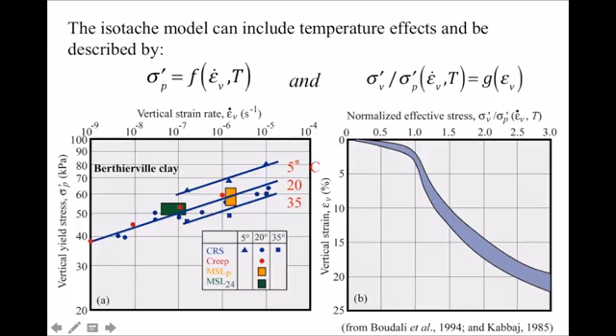So, in fact, the pre-consolidation pressure or vertical yield stress, which was a function of strain rate, is also a function of temperature. And this is shown here for the Berthierville clay, where you have the line in the middle at 20 degrees, the upper one at 5 degrees, and the lower one at 35 degrees. But when the vertical effective stress is normalized with respect to the pre-consolidation pressure associated with the temperature and the strain rate, at that time, all the data come in a very narrow band.